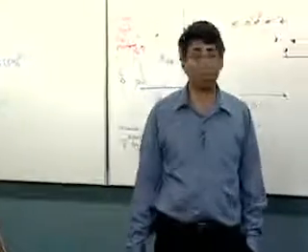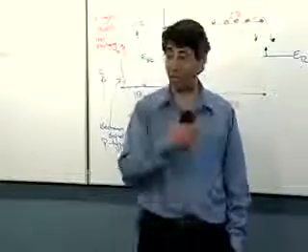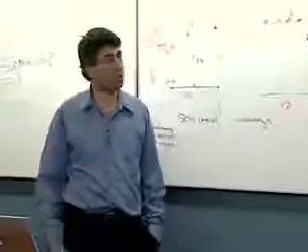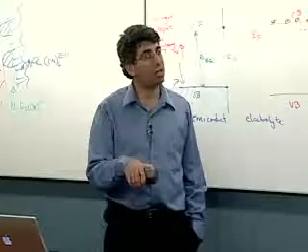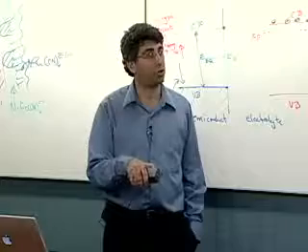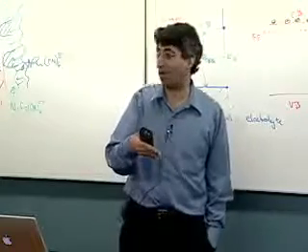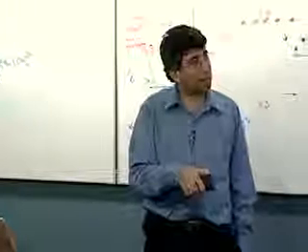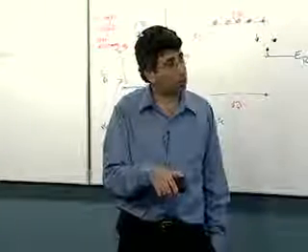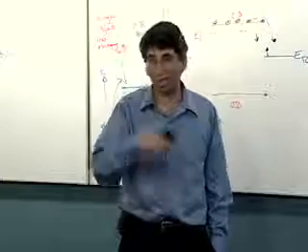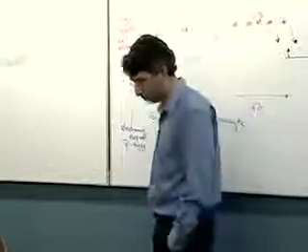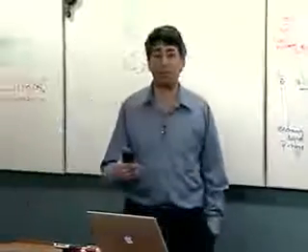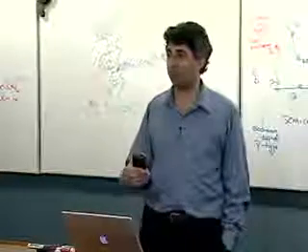Another way you might do this is play with the charge transfer kinetics at the interface, which the Lewis group has specialized in, and tweak that interface either by changing the nature of the semiconductor at the surface or by chemically modifying the interface or throwing in an appropriate solution redox couple, so that you can get the rate constants for what you want to be large and the decomposition rate constants to be small. Typically, where people have been successful in doing this, they've had to shut off the rate constants for oxidation of water also.